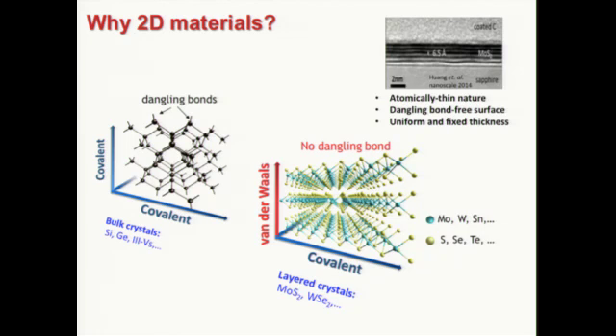Also, as you see in this TEM image, they are very uniform. That's a big advantage because technically we can thin down silicon to a few nanometers, but there is always 1 to 2 nanometers of roughness. That's not a big deal when we are dealing with a 10 nanometer film, but in a 3 nanometer film, 1 nanometer is about 30% variation, and that induces a huge device-to-device variation. But in this class of material, the thickness is very uniform, and that's a big advantage here.